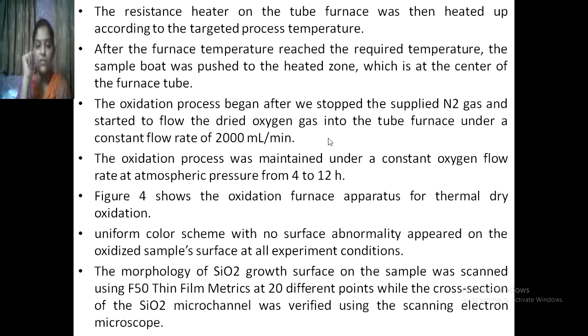So the oxidation process was maintained under a constant oxygen flow rate at atmospheric pressure from 4 to 12 hours.